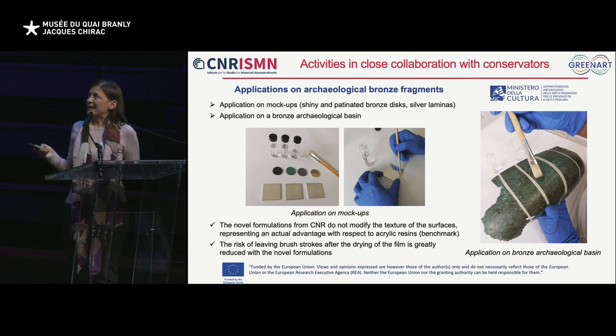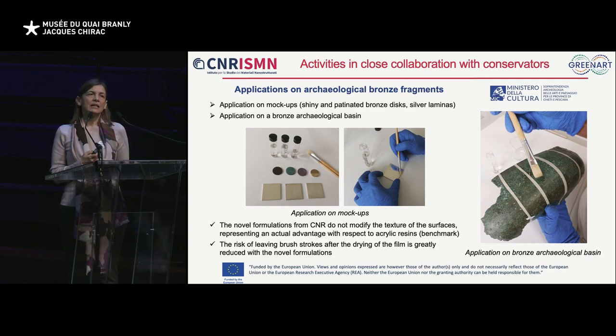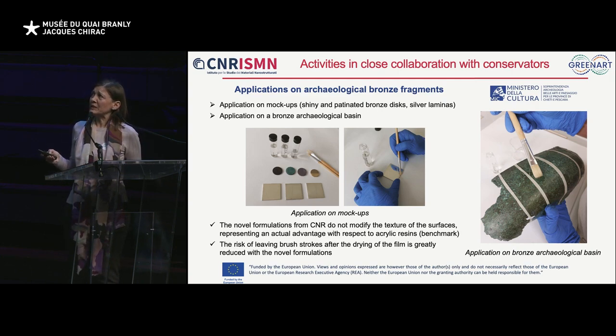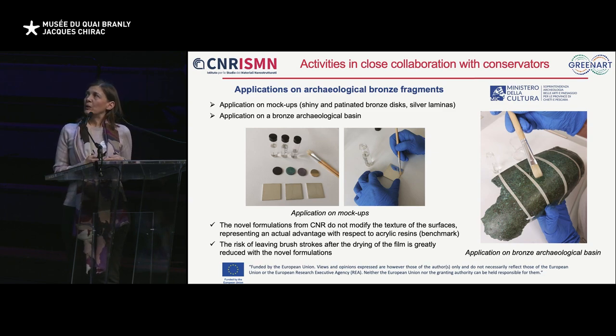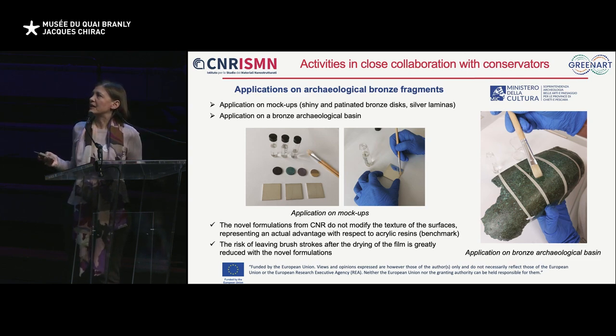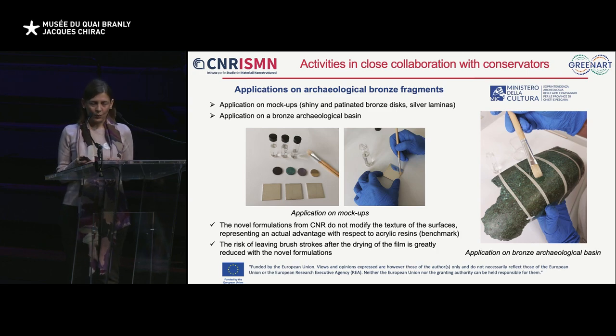So I can just anticipate that in any case, one of the first feedbacks was that with the new products, we don't modify the texture of the surface, on the contrary, with respect to the commercial products, like those based on acrylic resins. And in addition, the risk of leaving brush strokes after drying is lower.